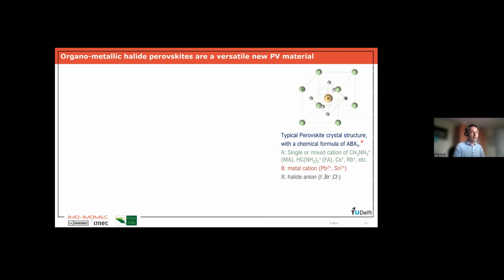So there are magnetic perovskites, there are superconducting perovskites, there are ferroelectric perovskites. You have a lot of different perovskite materials with different properties. Here we are talking about photovoltaic perovskites, and there typically the A ions are the organic material. So they are single or mixed cations of, for instance, methylammonium. Then you have a metal cation, the B material in the center, which is typically lead for the best devices, but it can also be tin. And then the X elements are, in our case, iodine, bromine, or chlorine.